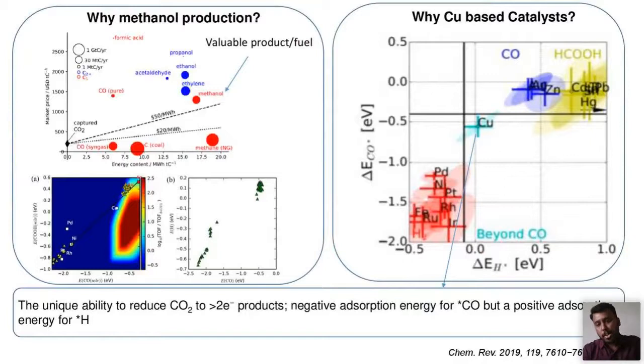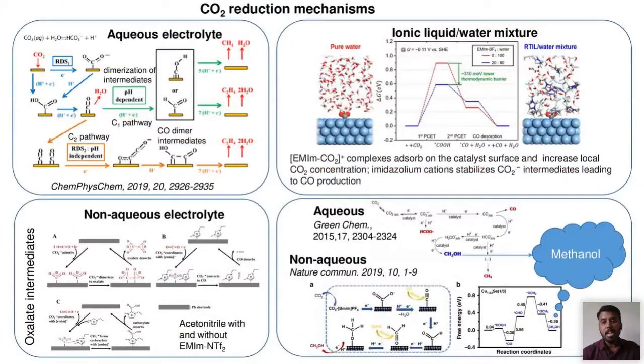And mostly in CO2 reduction, copper based materials are used. The main reason for this is that copper has the unique ability to reduce CO2 to more than 2 electron products. It has a negative adsorption energy for CO, and is the only metal with a negative adsorption energy for CO but a positive adsorption energy for hydrogen. That's why people are using copper as a catalyst for CO2 reduction.